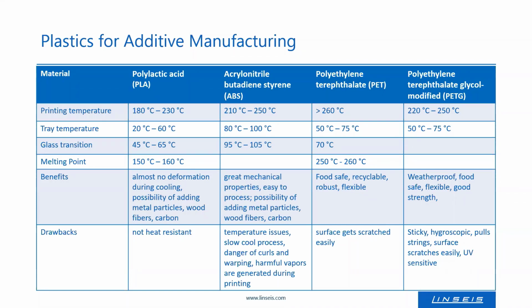ABS is also a very commonly used filament material. The advantages are that it's robust, really light, cheap, and available in many colors. It also offers the possibility of adding metal particles, wood fibers, carbon, or some other materials to the filament, so that one has in the end a combined material. So by that one also combines their mechanical properties. The printing temperature here is a bit higher, from 210 to 250 degrees Celsius. And due to these higher temperatures, a heated tray is really necessary, not only recommended. And here the temperature should be between 80 and 100 degrees Celsius.